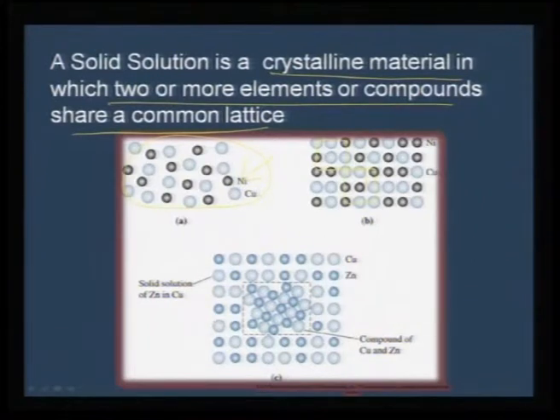For example, if you take the case of copper with nickel, nickel and copper both form FCC structure. As a result, over the entire range of doping, it is possible for you to keep doping nickel into copper or copper into nickel. As a result, you can see an FCC pattern is always there, but the only thing is in every FCC unit cell you would see the random distribution of copper or nickel. But when you take zinc in copper, for example, zinc has a different crystal structure compared to copper, and as you can see, two things can happen. One, to some extent zinc can go into copper, therefore it is a solid solution because they are arranging in a periodic way. Only thing, the distribution of zinc in copper is random.